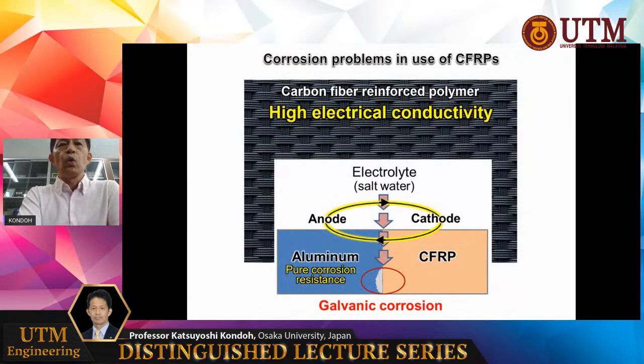So that is the reason shown here. For example, carbon fiber reinforced polymers have very high electrical conductivity due to the carbon fibers. However, if the carbon fiber materials contact aluminum materials, aluminum unfortunately has very poor corrosion resistance. At the interface, they form an electrical circuit, and CFRP becomes the cathode and aluminum the anode. So due to the electrical circuit, the difference of electrical charge causes very large and severe galvanic corrosion